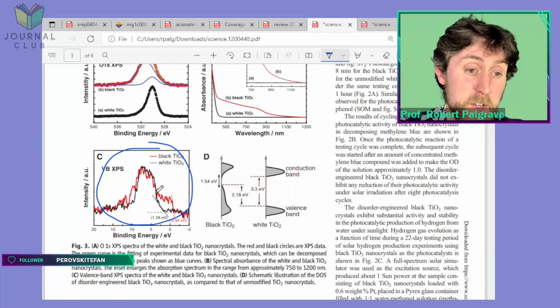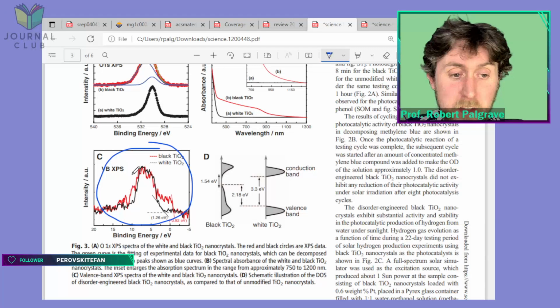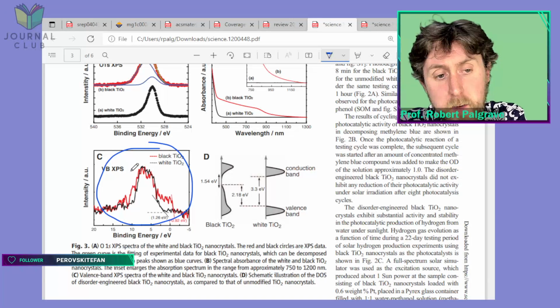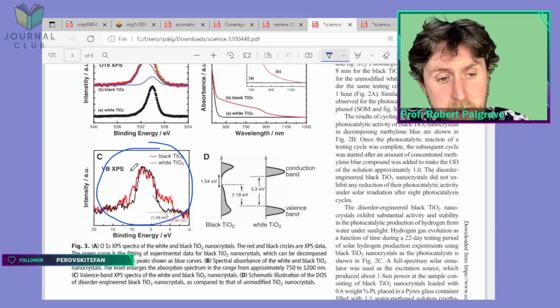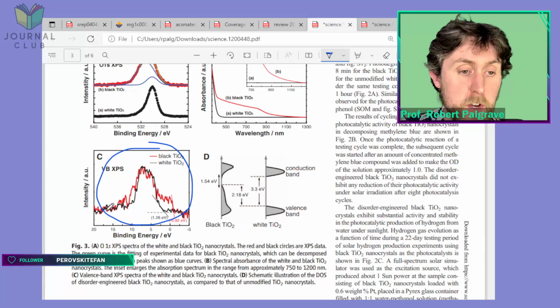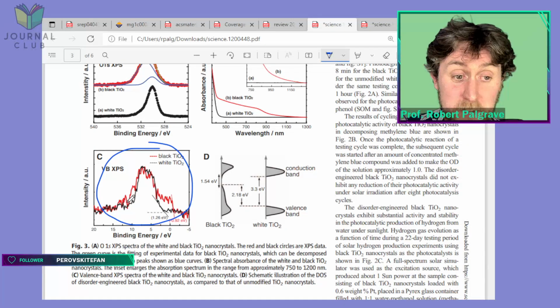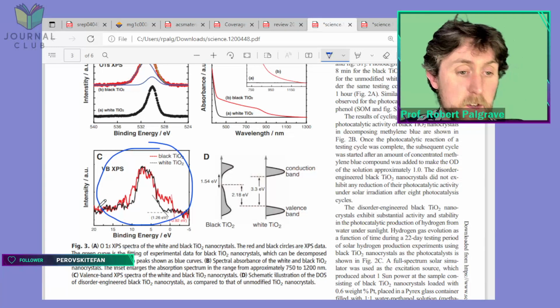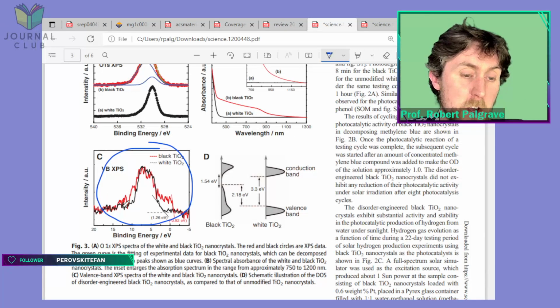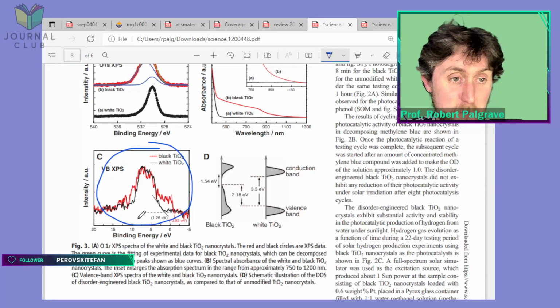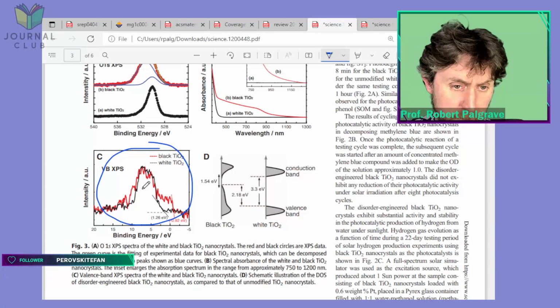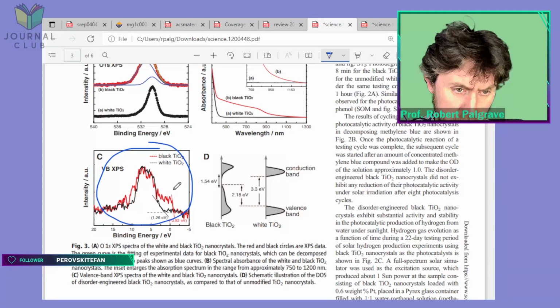This peak is much more intense than the valence band, but these days with modern equipment, even 10 years on from what we see here, it's much easier to record much less noisy, high signal to noise ratio valence bands. So you can get much smoother spectra here. So it was kind of interesting to see just how noisy this was, published in a top journal just 10-11 years ago. Anyway, they showed some important differences here.